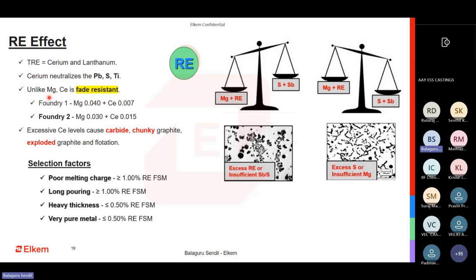In case of FSM, the cerium is very, very fade resistant. So having rare earth is not only beneficial to neutralize the trace elements, at the same time it also forms nuclei. The nuclei it forms are very, very stable. Take Foundry 1, which has a residual magnesium of 0.040 and a cerium level of 0.007, versus Foundry 2, with a magnesium of 0.030 and 0.015 cerium. This is more stable. What do I mean by it? The cerium at 0.015 is not going to fade for a longer time, meaning as long as the metal is liquid, this is not going to fade.